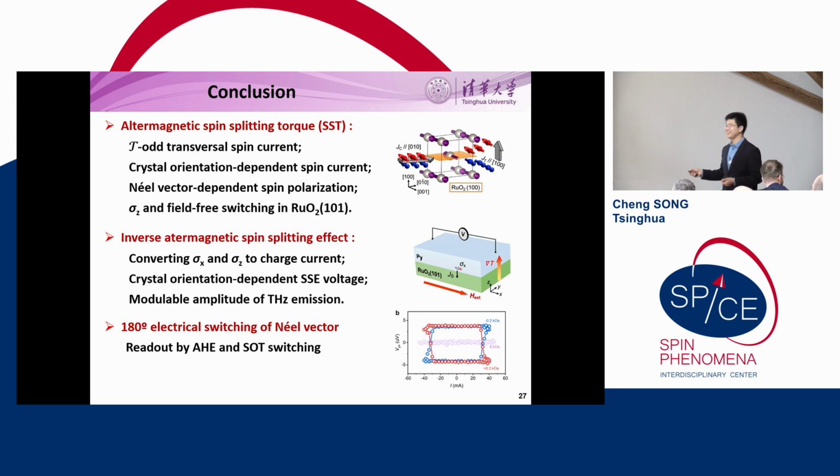Now I go to the conclusion. The first is we demonstrate altermagnetic spin splitting torque. We got time-reversal-odd transverse spin current. It shows crystal-orientation-dependent spin current and Néel-vector-dependent spin polarization. We got sigma Z and field-free switching in this ruthenium oxide (101) sample.